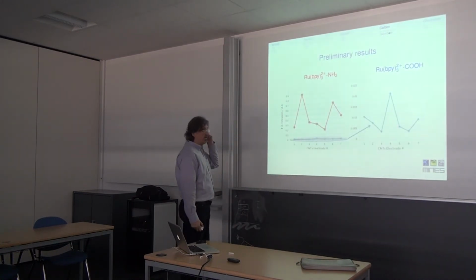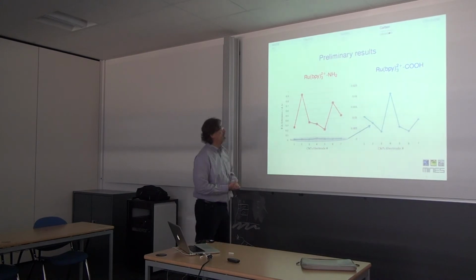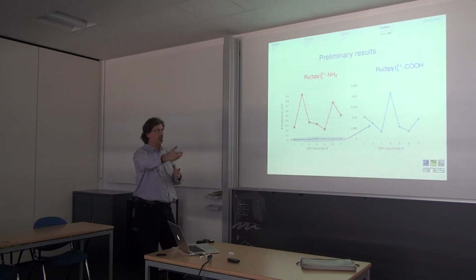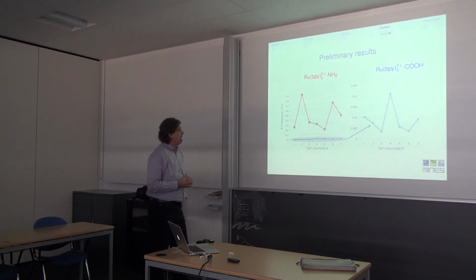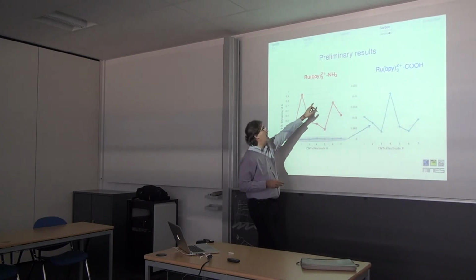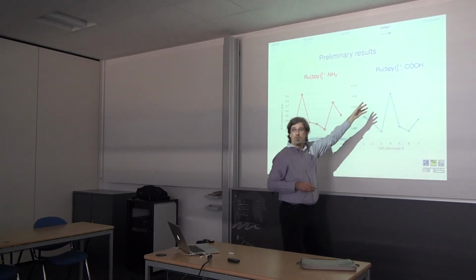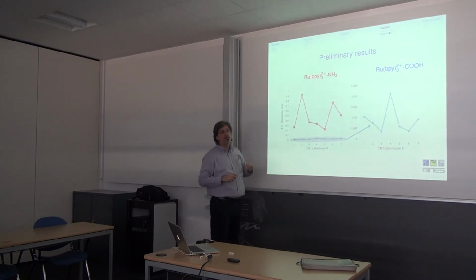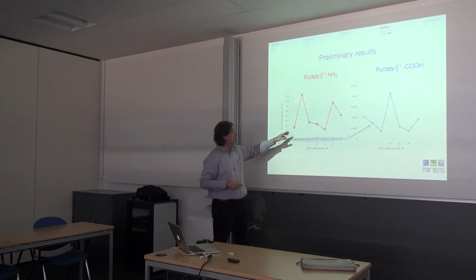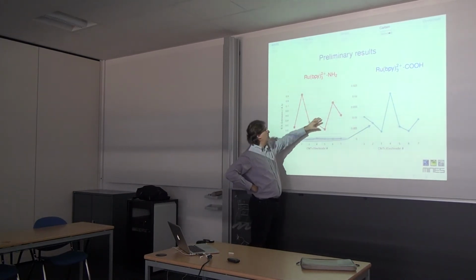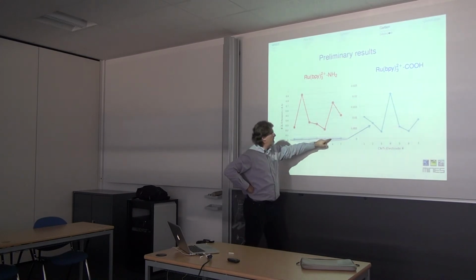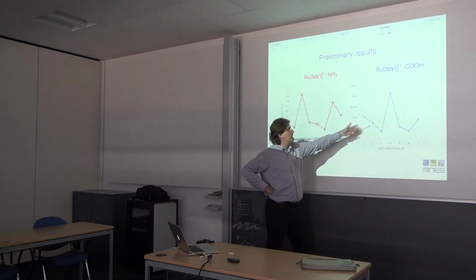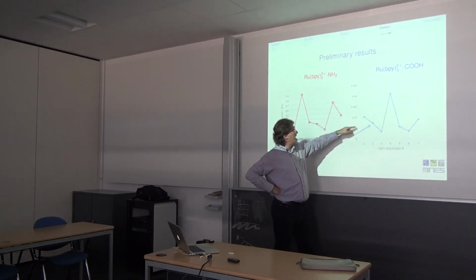And these are the results. Let's comment these results because it's one of the starting points for what I will do next. You see, we used amino group or carboxyl group for doing the linking. And the efficiency was very different from the two. You see, using amino group the emission was very good. In terms of using the COOH group, you see, it was very much lower. And these are the measurements we had with